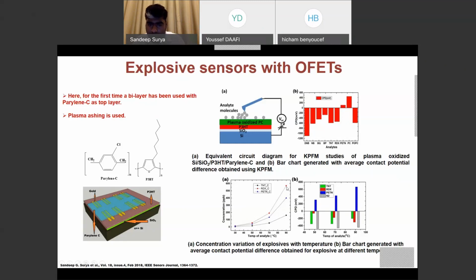In the case of RDX, for PETN, it was around 120. So as one can see, as you increase the concentration from the KPFM analysis, the CPD values were also increasing linearly towards the end. So thus it comes to an end because this is a different OFET with different approach. This is another paper that we published in IEEE Sensors Journal.